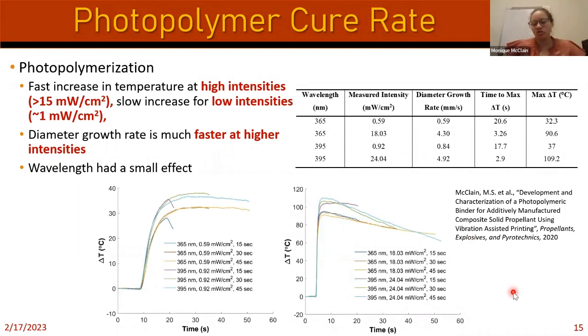This is just of the photopolymer itself. Just to orient everyone, here was our test matrix. We had 2 different wavelengths, or gooseneck lights, that we could choose. Again, we measured the power of each of these lights, and before we tested, we measured the area of that light, so with that we can calculate this intensity value. You can see that we have 2 pretty low intensities and then 2 higher intensities. We also measured the diameter growth rate: what the final diameter was, and how much time we applied the light for, based off the IR image data.